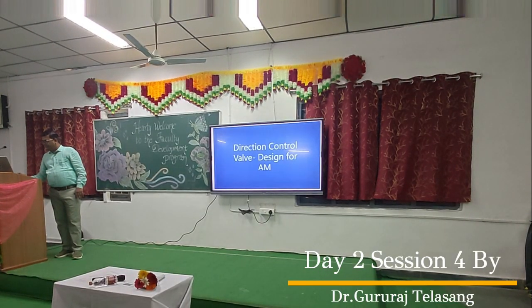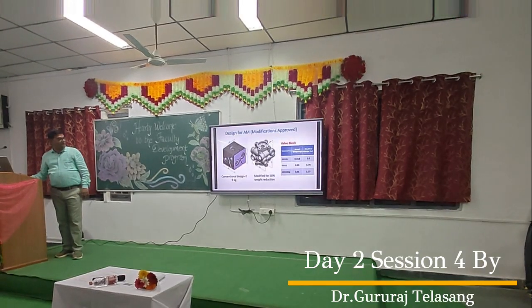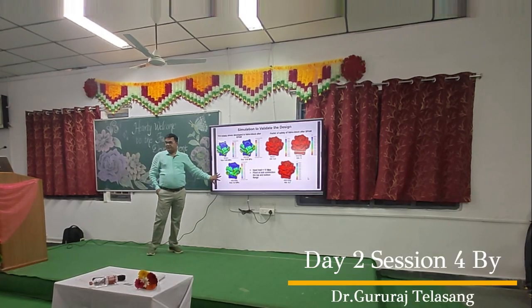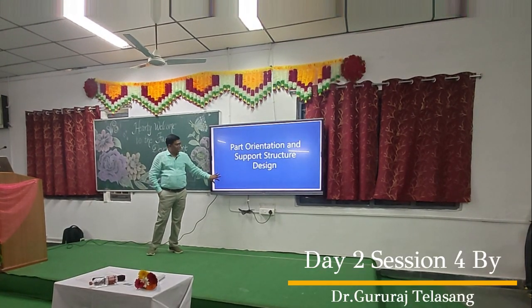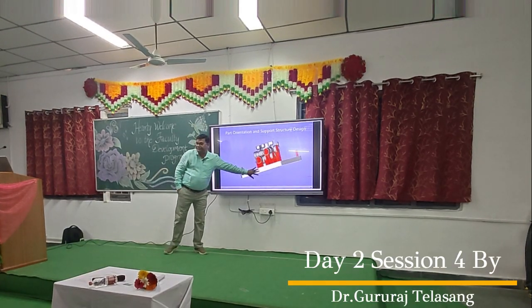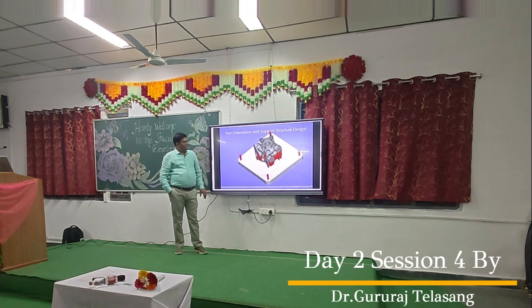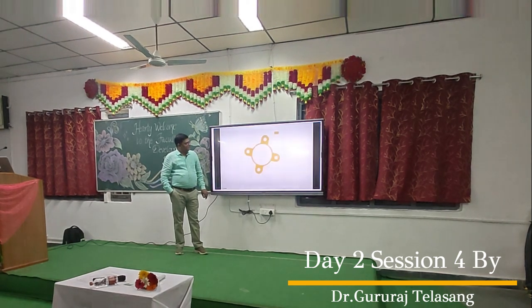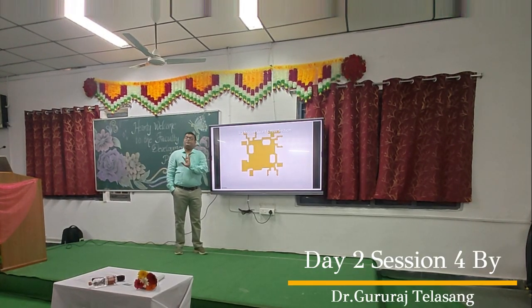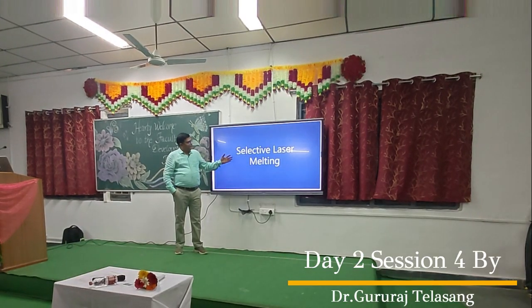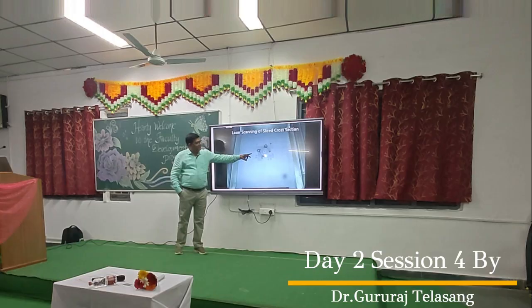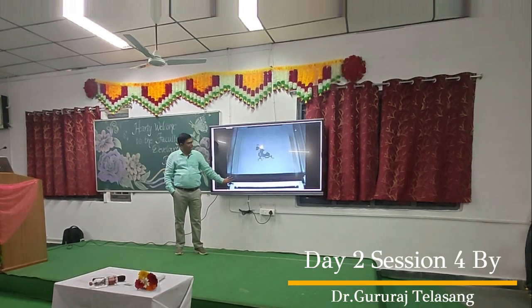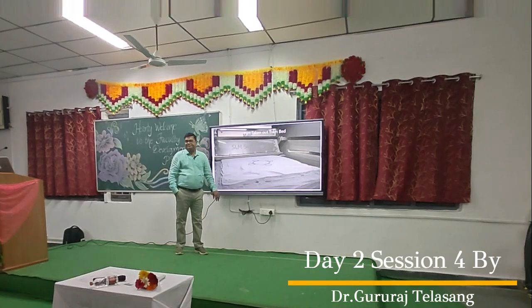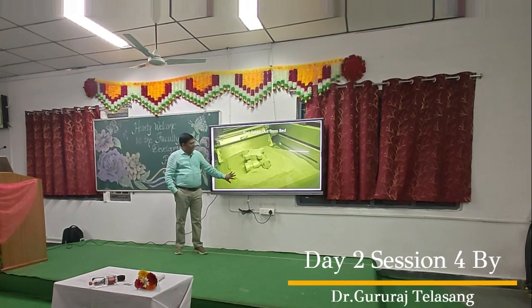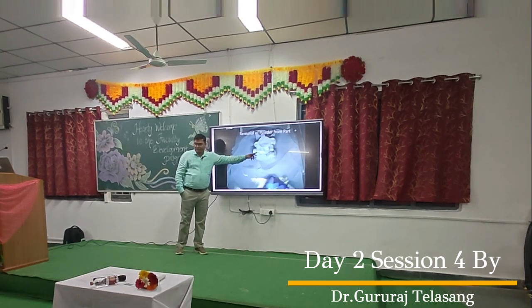I think this video is okay. This is the part. This is a simulation we did. These are support structures we have to give. Red color are support structures. So this we see virtually before printing. Is there any problem and all? Then actual printing now. So layer by layer it is getting printed. It's quite fast, but it's not that fast in actual. You can see support structure getting printed there. It's fine things. So this is the withdrawal of the part. There's loose powder here. We collect it back. This is the component.